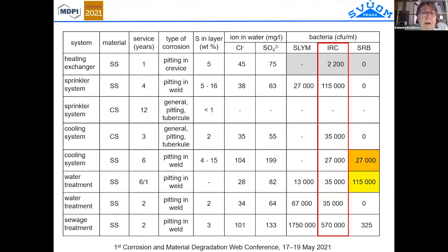When I summarize all these case studies, it was interesting to show what is typical for all of these cases: the penetration of the pipe wall material occurs in a relatively short time. One exception is the sprinkler system, but that is due to the relatively thick wall.